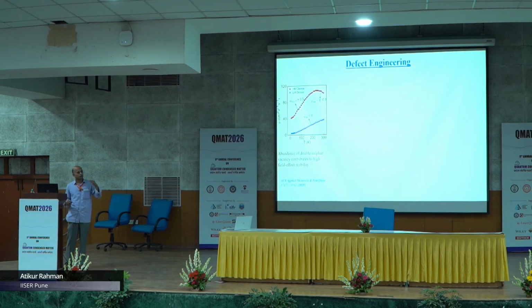And what we found through detailed study is that in these samples there is an abundance of double sulfur vacancies, which lie very close to the conduction band, and as a result you get very high mobility. You can even see the phonon limited mobility in these kinds of samples, whereas the MoO3 grown samples don't show that kind of behavior.